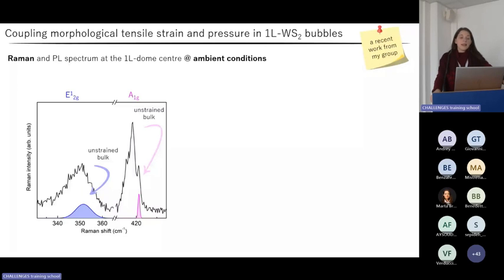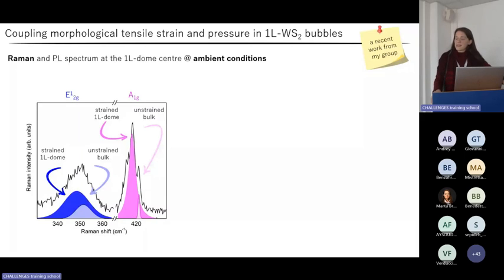Now let's have a look at the Raman and photoluminescence spectra collected at the dome center at ambient conditions. In the Raman spectrum, we can immediately recognize the E1 2G and A1G peaks of the bulk substrate centered at about 350 and 420 centimeters to the minus one, while the corresponding bands for the monolayer dome are visibly redshifted due to the application of tensile strain.